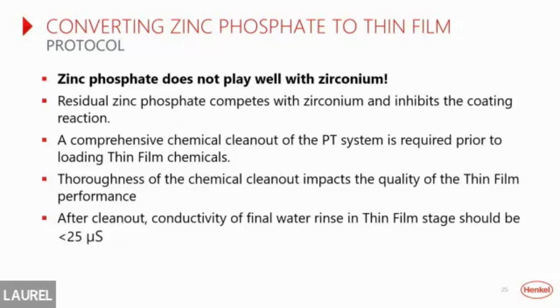Now, how thorough this cleanout is will impact the performance of the system. And typically, we even measure this after we do the cleanout. We will fill that last rinse up and measure the conductivity. I'm sorry, measure not only the conductivity, but something I forgot to add here, the parts per million of phosphate. Ideally, it should be less than 10 parts per million, but in practicality, we've seen less than 50 lead to successful cleanouts.